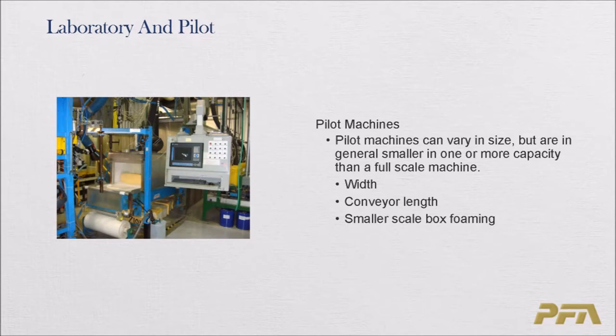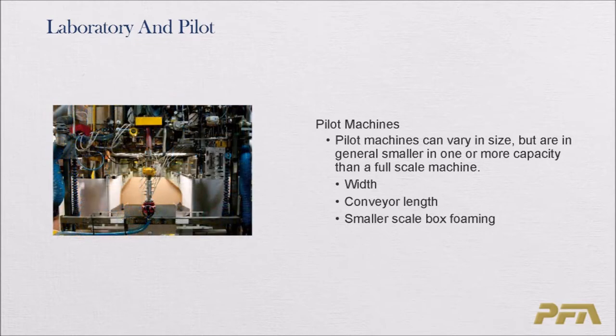The next step up from the laboratory is pilot scale or pilot machines. Typically these machines exist within the raw material supplier base. It's a very good tool for evaluating chemistry and giving a good indication of how it's going to perform on a production machine. There are a few foam manufacturers that have pilot scale machines as well. It's a good tool to scale up from the laboratory and go through that transition before going to full scale. Bear in mind that full scale is 800 to 1,000 pounds per minute of raw materials on a continuous scale, so that can chew up a lot of material and cost.